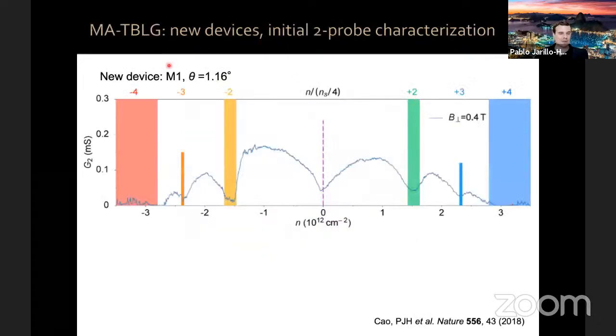These are data for a new device with an angle of 1.16 degrees. These are data with a small perpendicular magnetic field applied to it. You can see, similar to before, V-shaped conductivity near charge neutrality, no conductivity at 4 electrons and 4 holes per moiré unit cell. You can see a deep conductance dip at 2 electrons, 2 holes per moiré unit cell. Other stuff happens at minus three. A lot more is happening that I'm not telling you about right now.